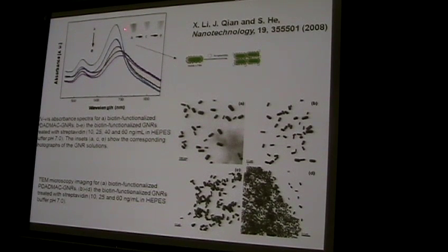The physical reason a small concentration change in streptavidin causes such a big spectral peak shift is that the streptavidin attaches these gold nanorods through bioconjugation, and with a different concentration they have completely different aggregation, and that will certainly cause a bigger spectral shift in this case.